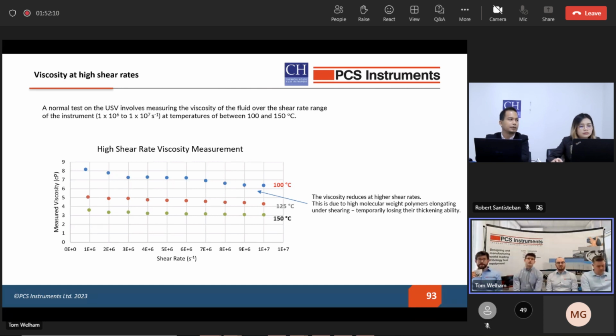So the plot here shows an example of shear thinning with a significant drop in viscosity between 10^6 and 10^7 per second shear rate. And this is the kind of thing that can be measured with the USV. And this is the sort of behavior that will be seen in a real application if it reaches shear rates of this magnitude.